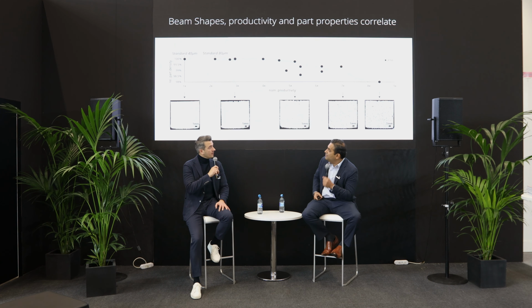No. I think with standard lasers, depending on the materials, you go to 3-4 layers to like 5-6 layers, depending on what your penetration depth is, what your power is, and what the melt pool characteristics are. But with a wider beam and with a more distributed power profile across the density distribution on the spot size, we've been able to get like 1 to maybe like 1.5 layer thicknesses deep. I think we're still closer to conduction welding. We're not completely there yet, but I think that's a substantial step forward in our journey to trying to achieve that kind of a welding profile. Yeah, I would say. Okay, thanks.